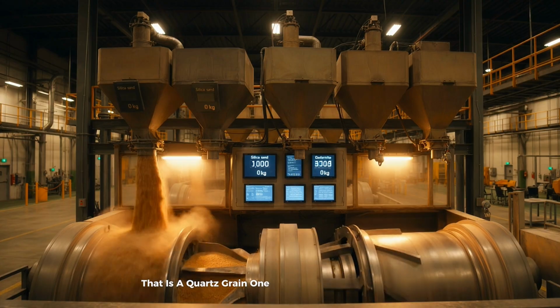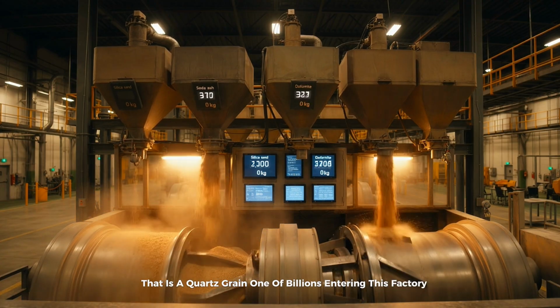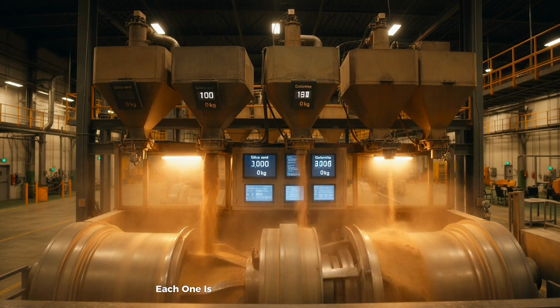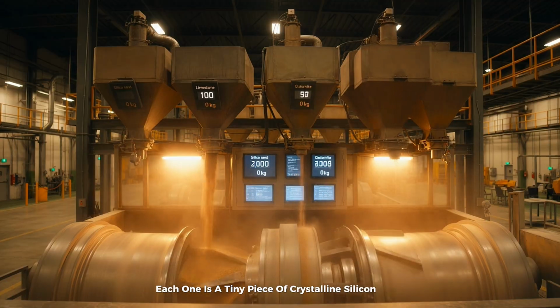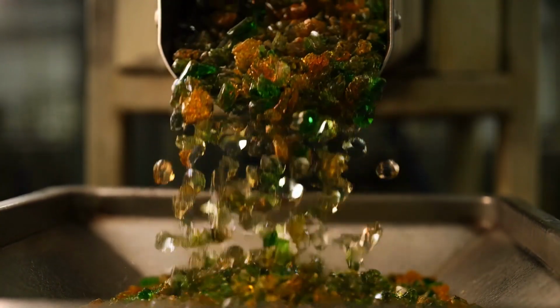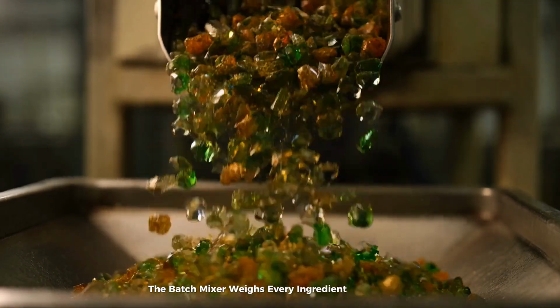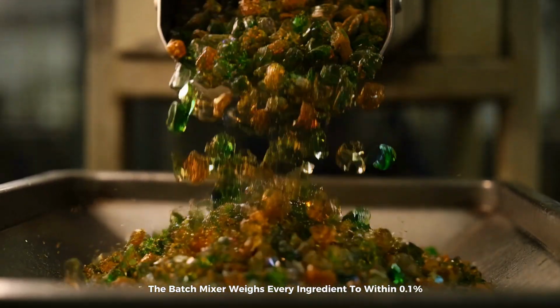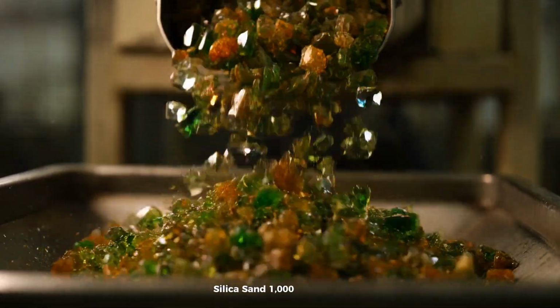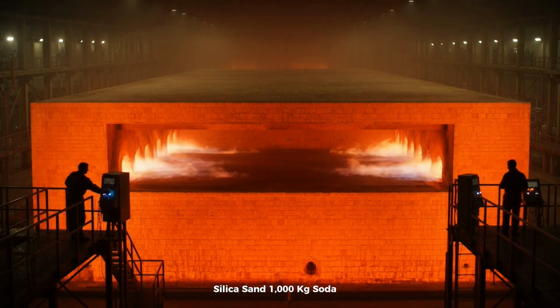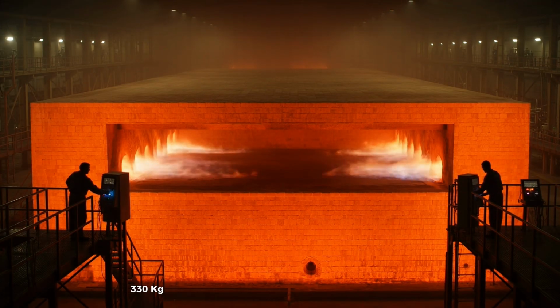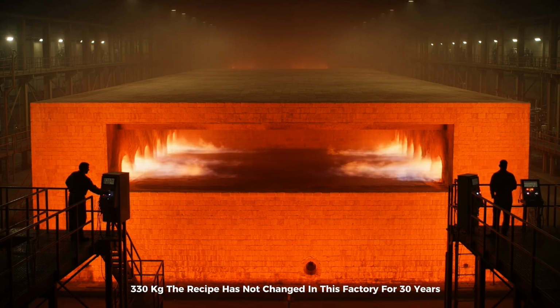That is a quartz grain. One of billions entering this factory today. Each one is a tiny piece of crystalline silicon dioxide, the same material that becomes the glass in your hand. The batch mixer weighs every ingredient to within 0.1%. Silica sand, 1,000 kilograms. Soda ash, 330 kilograms. The recipe has not changed in this factory for 30 years.